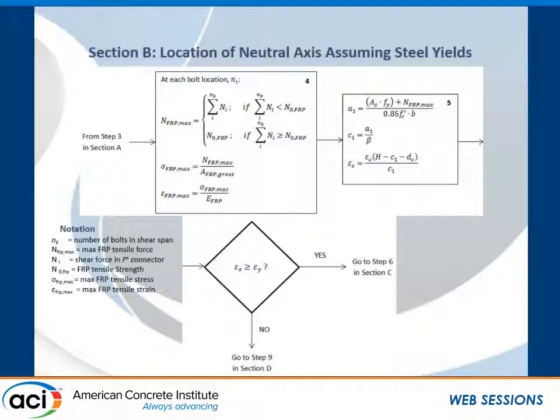Maximum stress in the FRP is calculated, and that's based on the gross area of the FRP. And then we get our FRP strain from Hooke's law. Now, the concrete stress-strain relationship has to be assumed to determine the location of the neutral axis. For cases where the concrete was at or near crushing strain, we used the typical Whitney stress block, and based on that, we're able to locate our neutral axis.